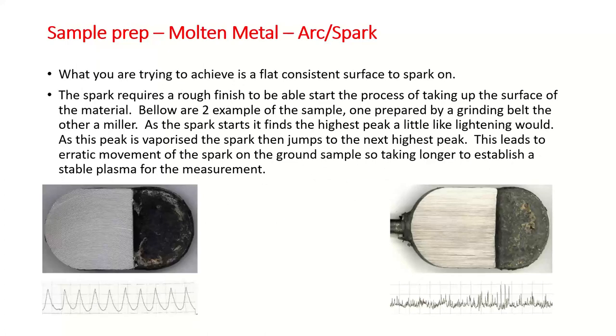So the reason for this is when you're actually sparking a sample, the spark is a little bit like lightning. It will find the highest part first. So if you look at the two samples there, we've got one on the left-hand side, which has been done on a milling machine, and the one on the right-hand side has been done on a grinder. And if you drag a stylus across there and have a look at the roughness of the surface, you can see on the milled surface that it's a very uniform surface, a very uniform peak. So when the spark gets on there, it's going to hit one peak and it's going to stay in the same sort of area, and it'll slowly move itself out. It'll not be jumping around.